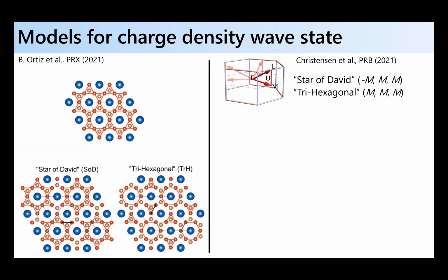They're all 3Q distortions. Okay, with the symmetries, the distortion being the wave vector pointing to the three equivalent endpoints in the Brillouin zone. And the only difference between them is that the phase of one of these 3Qs can be flipped relative to the other. So basically, it's like running one distortion in reverse. Okay, so this is just a two-dimensional case, meaning I'm just thinking about a single layer, what's energetically favored. So DFT tells you these two distortion types are rather close to one another.